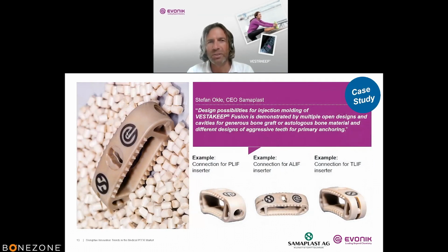And yeah, we established with them a white paper and tried to create a sample cage which would not make sense at all as one single part. So it is not a cage, it is really a sample part which shows different access points which are possible to injection mold. So it should also generate openness to switch from a potential machining idea to say, oh, why don't we actually injection mold? Yeah, and so they did a great job in developing that in a very short time. And we injection molded then our VestaKeep Fusion, and it worked out perfectly.